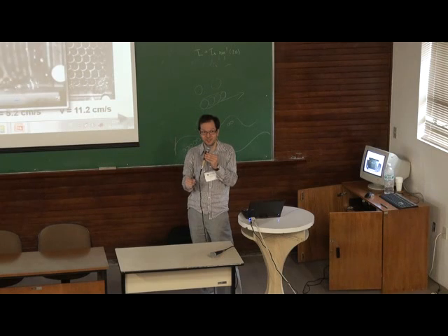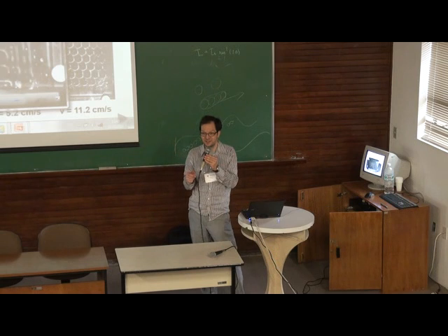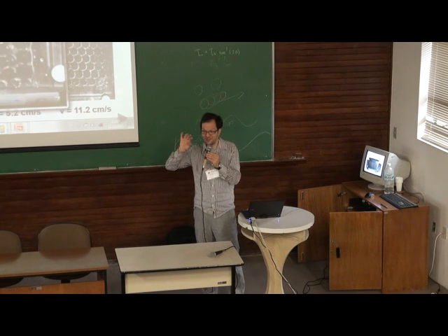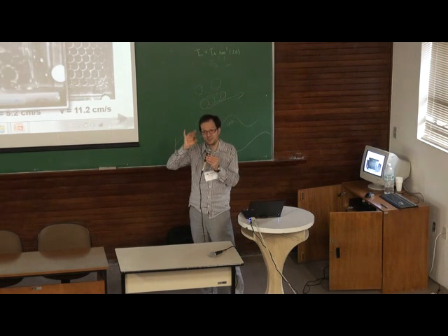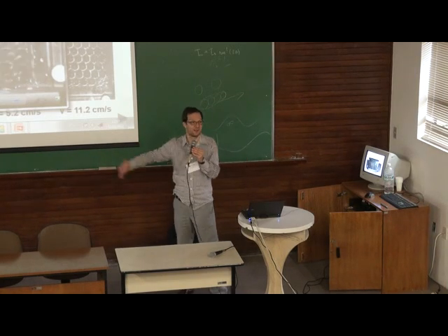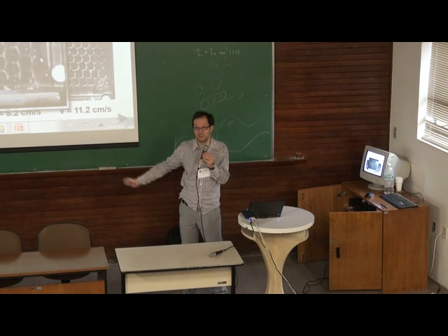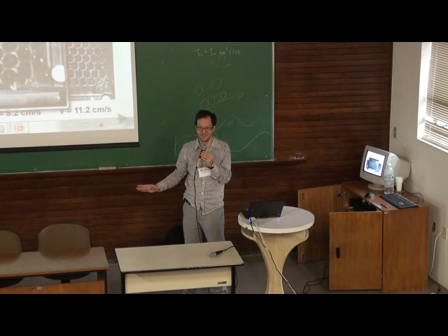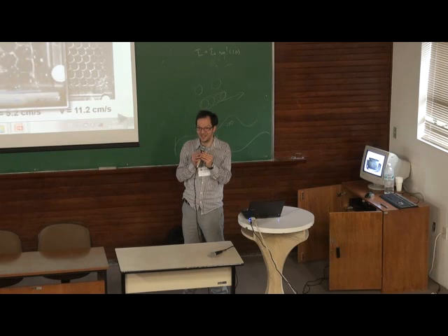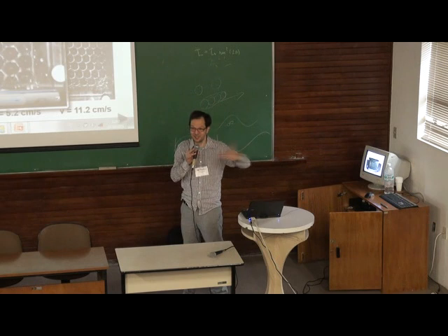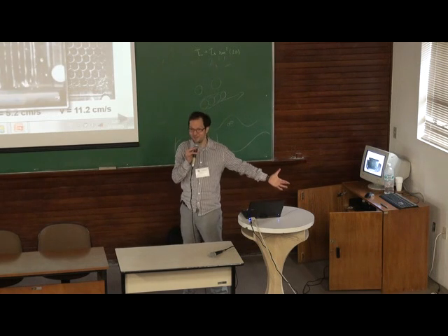The Brownian relaxation time is of the order of 10 to the minus 3 seconds, so it's in the kilohertz regime. There, everything is very sensitive to the size of the aggregates and so on. Here, not. Here you have just some kind of almost static magnetization curve. Here the complex susceptibility is of no importance. So that's quite a difference: ferrohydrodynamic pumping is in the kilohertz regime, and we are here in the millihertz regime.